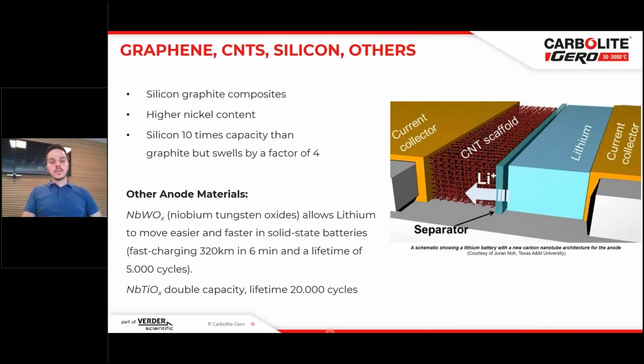And many different anode materials are optimized in that way, for example, niobium tungsten oxides are added and used because they allow the lithium to move much faster. And that means, as shown in this example, that there is a fast charging possibility for 320 kilometers within 6 minutes. So it's a very important thing to combine many different materials and to find their best usages, so that the materials and the batteries have a great chance to change our daily life.